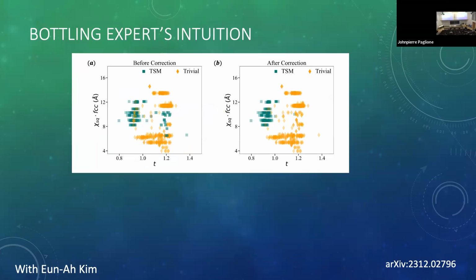So here's a plot which shows, at the bottom, it recovered our tolerance factor, our distance ratio. And then here it found a component which is the electronegativity of the element on the square net multiplied by the ionic radius of this element if it were in an FCC crystal structure. And so it can split the data quite well, although you see it's not perfectly separated in green and yellow if it uses these two components.